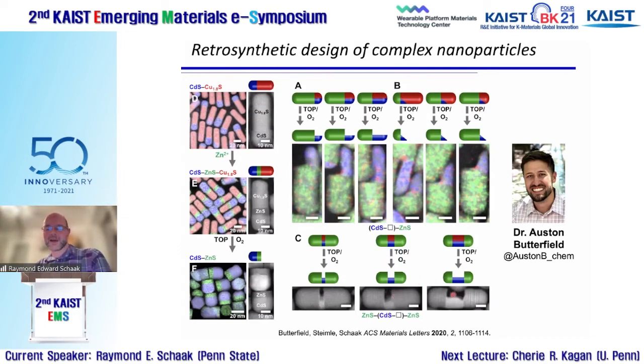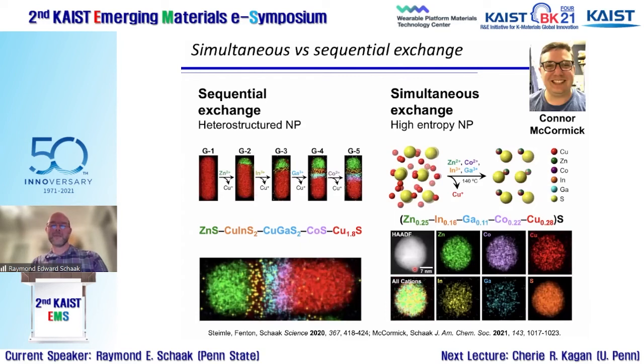or taking it a step further, being able to control gap sizes through engineering in the width of how far the zinc sulfide is exchanged from the end, to control how much space is in the gap, installing a cadmium sulfide notch on it, and then removing the copper sulfide. So this is starting to feel a lot like how you might approach a molecule synthesis through these multi-step reactions.